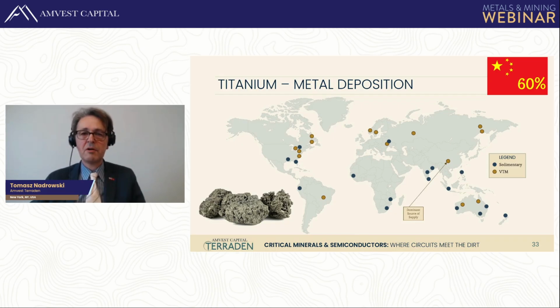Titanium, another of those barrier metals, important, very inert metal. Helpful always when metals and metalloids connect, sometimes generating a lot of resistance. So to deal with the power consumption, titanium is interspersed. Most titanium is produced from heavy mineral sands, sedimentary, from rutile mineral specifically, but there are also VTM deposits, so vanadium titanium magnetite, such as in Sichuan in China, and Bahia in Brazil. So again, China is quite dominant in the production of titanium, although there are two markets here, titanium dioxide for paint and titanium sponge metal, which is only less than 10% of the total market.